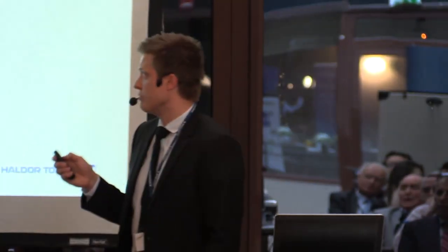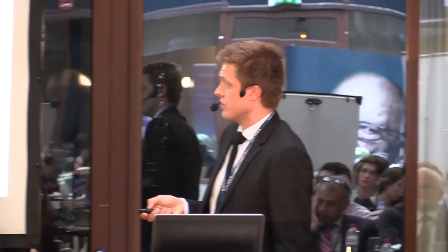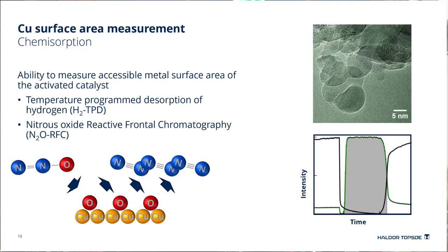Similarly, we had a nitrous oxide reactive frontal chromatography experiment, which is similar, but slightly different. It's a flow experiment. So you come along with nitrous oxide, then you react it with your metallic copper surface to form a copper oxide and a nitrogen molecule. And this process can continue as long as you have metallic copper present in the catalyst. And at some point, there's no more copper and you have a breakthrough of nitrous oxide.